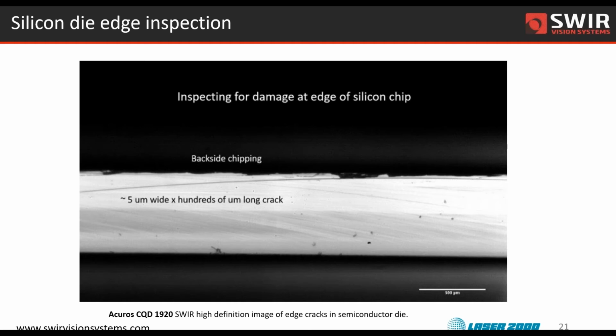This is another neat application where instead of looking at the die from the bird's eye view, you're pitching it on the edge, and you're looking through the long end of the die, trying to see cracks that are occurring in the die itself. So cracks, and you can see there's a small 5 micron wide, hundreds of micron long crack that's formed here. This is being illuminated from the back of the die into the camera using SWIR LEDs. And so this is another place where you're really taking advantage of the fact that those SWIR photons are able to give you information you're not getting in the visible. So that's a die edge for crack inspection.